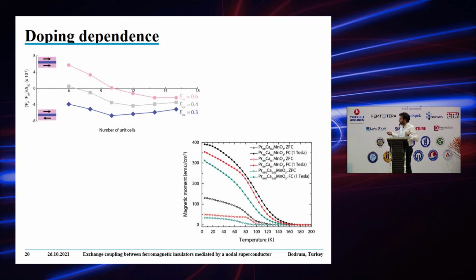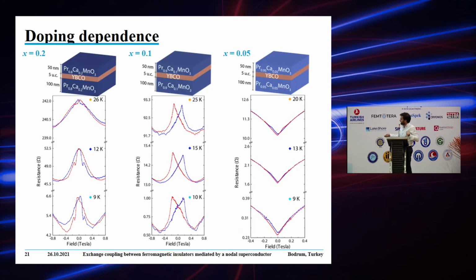And then we also did some studies as a function of doping, because this is another thing that the manganites allow you to do. Of course, if you decrease the exchange energy of the ferromagnet, so delta, the superconducting condensate energy becomes larger, then you would expect that the anti-parallel state is favored. And that's exactly what we did. I don't have a lot of time, so I'll just skip through this, but that's exactly what we did.